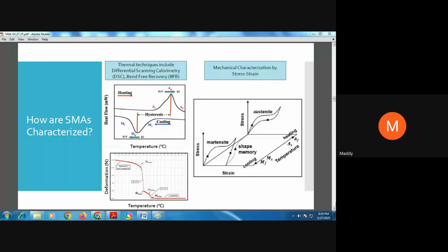Right below this is what is called bend-free recovery, and what you do here is you apply a pre-strain on the material in the colder phase, which is the martensitic phase. Typically, I would say 1 to 3% strain is applied, and then you slowly start heating the material. And as I told you earlier, you generate recovery stresses, right? So as the transformation happens, you plot the deformation as a function of temperature. Now, the bend-free recovery is typically used on fine products, after the ingot is processed and then converted to fine wires, fine tubes, or even fine sheets. This is the most appropriate characterization technique, I would say. And as a derivative of this technique, you have the uniaxial pre-strain free recovery and a bunch of other similar free recovery tests. But these are the two predominant thermal characterization techniques that are used.